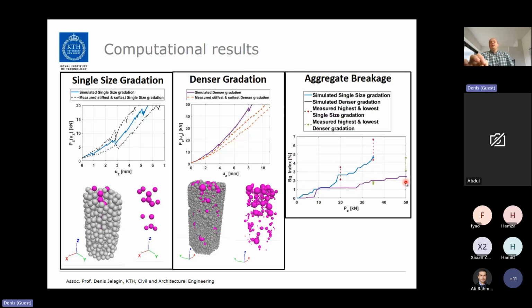And you can see that for dense gradation, where no additional calibration has been performed again, the model captures experimental results quite well, which is a good indication that the contact and damage laws we developed capture the physics of the system reasonably accurately. So that was a little bit on different aspects of large deformation behavior of different stone-based materials.